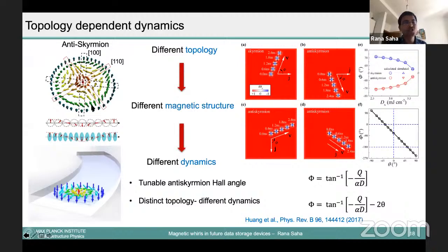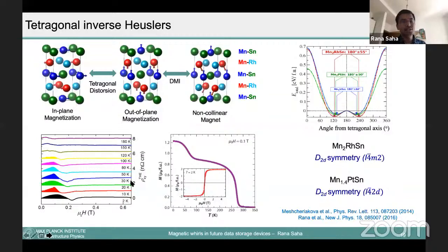So this is the structure of anti-skyrmion, where it is expected, because of some anisotropic structure, it can move in a straight line. So we use this material. This is called tetragonal inverse Heusler material, which we got in collaboration with Professor Claudia Felser's group. This is a metallic material with tetragonal symmetry, and to stabilize this kind of material, you need to have a particular symmetry, which is called D2d crystallographic symmetry.